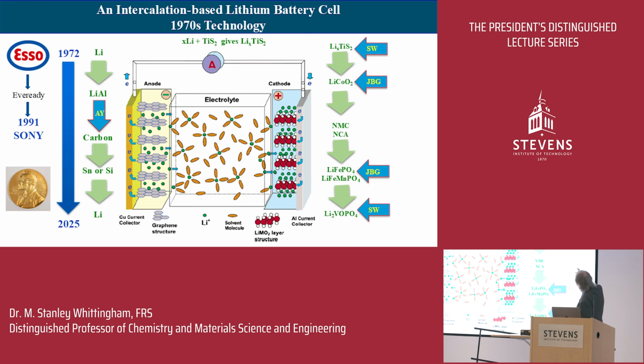The cathode side, we work with titanium disulfide. And that's the picture here. Layered structure, works exceptionally well, but its energy density is fairly low. So John Goodenough, who was at Oxford at the time, was working on cobalt oxide for its magnetic behavior, saw our paper and said, hey, my compound has a strange structure. It should work. Now, any self-respecting chemist knew it wouldn't work, because if you take lithium out of this compound, you've got cobalt 4+. Cobalt 4+ doesn't exist. John didn't know that, so he just did it. And it worked.